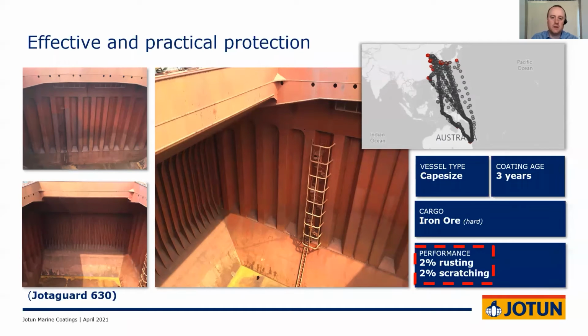The trade has predominantly been carrying iron ore, which, as you would know, is quite a hard cargo. And yet you can see that the coating is still in very good condition after 3 years, with around 2% rust and scratching, meaning that at this intermediate docking after 3 years, only minor repair is needed, versus what we would expect to be a much larger refurbishment being needed for a standard universal epoxy.